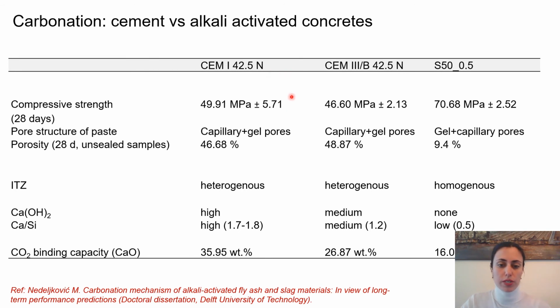And then to go further to explain, although the compressive strength of alkali activated materials is so high at 28 days and the microstructure is so dense compared to CEM1 concrete and CEM3B, and even the porosity is consequently also much lower compared to porosity of CEM1 and CEM3B. The calcium hydroxide makes a huge difference, and also the amount of calcium oxide that is inside the matrix of CEM1 and CEM3B. That consequently means that the CO2 binding capacity is much higher for CEM1 and CEM3B.